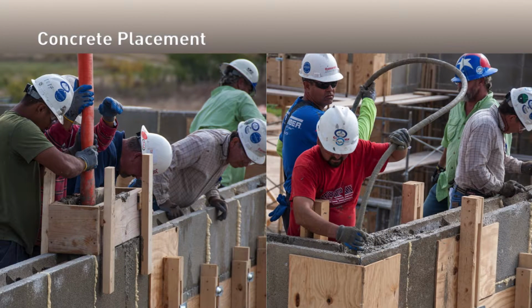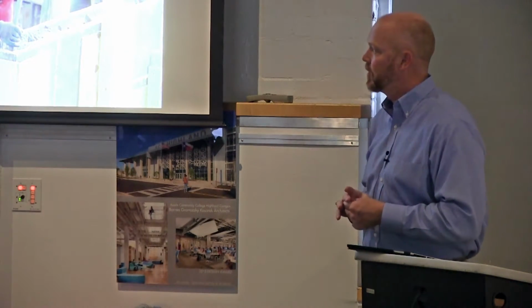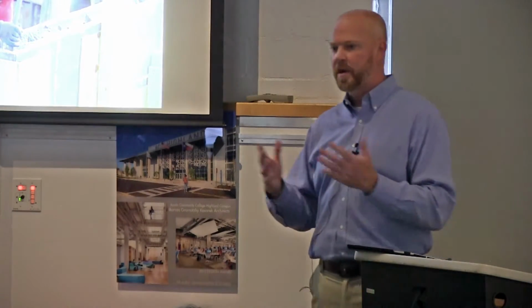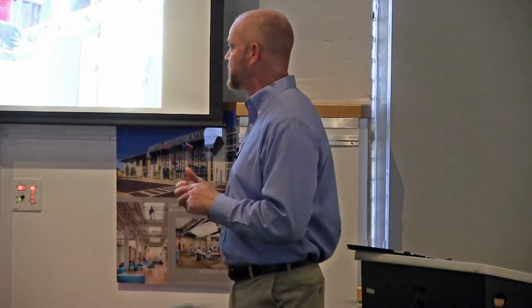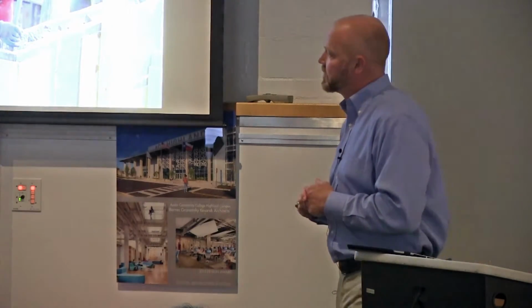Concrete placement's very important. You need to make the mix design correct. It's an ICF mix. It's an 8 to 9 inch slump, 3/8 inch maximum aggregate. Usually pea gravel or river rock's going to flow a little bit better. You might have a little plasticizer in there to get it to flow. We've done projects with design strengths between 2,500 psi and 7,000 psi. We did a hurricane-resistant wall in Galveston on Galveston Island. It had number 7 bars in it and 7,000 psi concrete. So you can get pretty high strengths inside the load-bearing portion of walls like this.